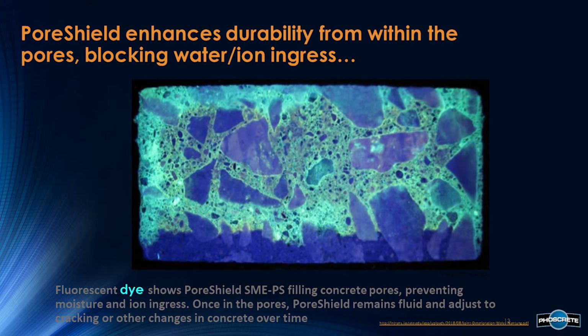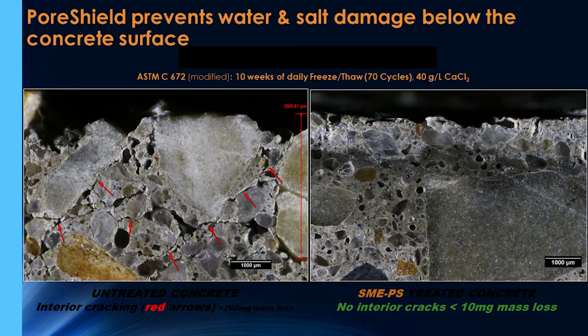As you can see here, you guys can mostly see it, the fluorescent dye shows the penetration of Pore Shield and how it fills the pore network to prevent future fluid ion absorption. So all that fluorescent light is the Pore Shield getting absorbed in the pores of the concrete, making them hydrophobic. These are high resolution photos that show the damage of 70 cycles of freeze thaw combined with a high concentration of calcium chloride. The samples on the right were first treated with Pore Shield and show no damage below the surface.